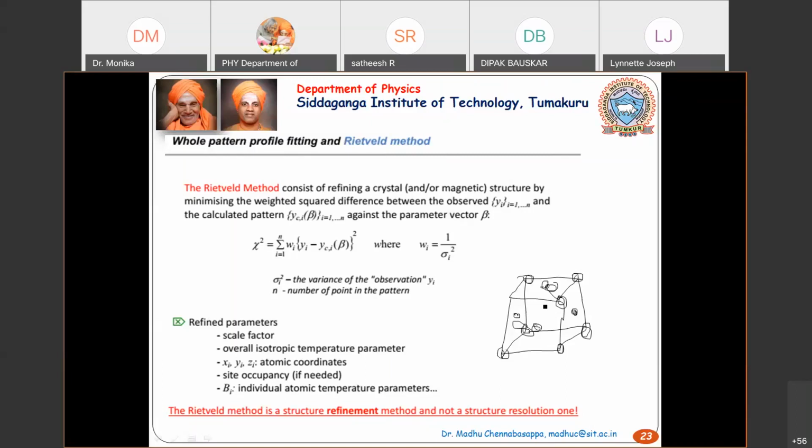Then for chlorine, I'm going to give 0.5 0.5 0.5. Then the rest is going to be regenerated. That means your foolproof program will generate the rest of them. Your neighboring atoms are generated based on the space group. As I'm saying, Fm-3m, it will generate the corresponding positions.